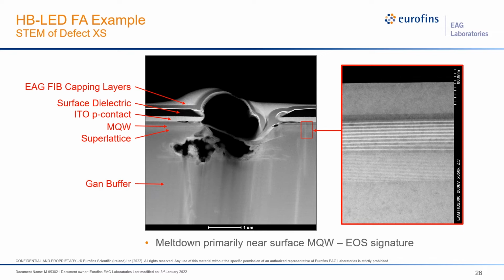And you can really see that the entire defect sort of spans across the junction, which you would expect. So it looks like, effectively, you had a short occur, and then all the current flowed through this region, which then led to the meltdown.